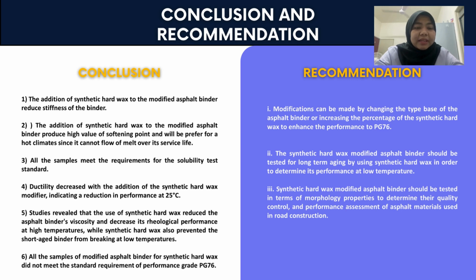Fourth, ductility decreases with the addition of synthetic hard wax modifier, indicating a reduction in performance at 25 degrees Celsius. This study revealed that the use of synthetic hard wax reduced the asphalt binder viscosity and decreased its rheological performance at high temperature, while synthetic hard wax also prevents the short-term aged binder from breaking at lower temperatures.